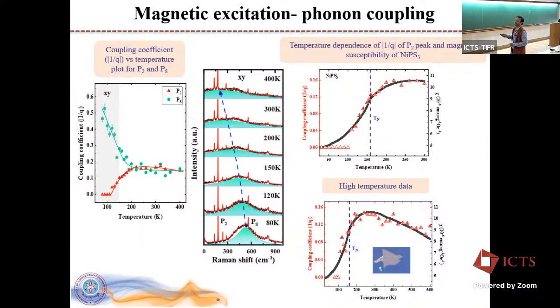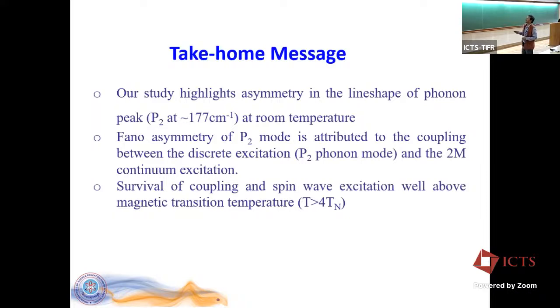Let's see. Here we have a more convincing result to show that this asymmetry has something to do with the magnetic degree of freedom. How? We plot here the susceptibility, up to about 600 Kelvin, which is 4 times the Néel temperature. The susceptibility doesn't show the 1 by T behavior; the tail is still not starting here. And the coupling follows the same behavior as the susceptibility. These 2 correlations convince us that there is indeed a relation between the 2 magnon and this phonon, which is giving this asymmetry. So I'll stop here. We learned that in NiPS3, the 2 magnon has a very interesting story to give us, and that persists even at very, very high temperature, and we believe there is something like paramagnon present in this system.